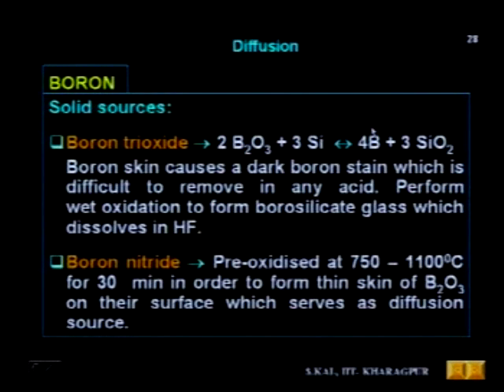If you use boron nitride, then you have to go for the activation of boron nitride, because through that activation process, boron nitride is changed to B2O3. One of the advantages of using boron nitride is that if you keep it in the normal atmosphere for a long time, it is not hygroscopic in nature. It will not absorb moisture. But B2O3 has a little affinity with H2O molecules, and if you keep it for a longer time in a normal environment, it will absorb moisture and form some different compound with hydrogen, oxygen and boron.